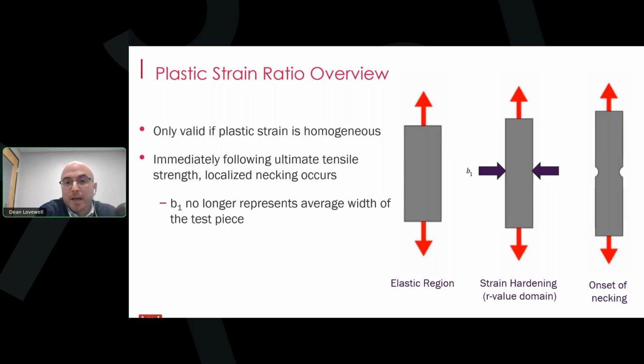We see that some necking has developed, and we know that as the test proceeds from here, all of the width strain is going to occur where that neck is. So whether the arms would happen to be at the location of the neck or elsewhere, it's still true that the transverse strain that they are measuring is not representative of the gauge width.